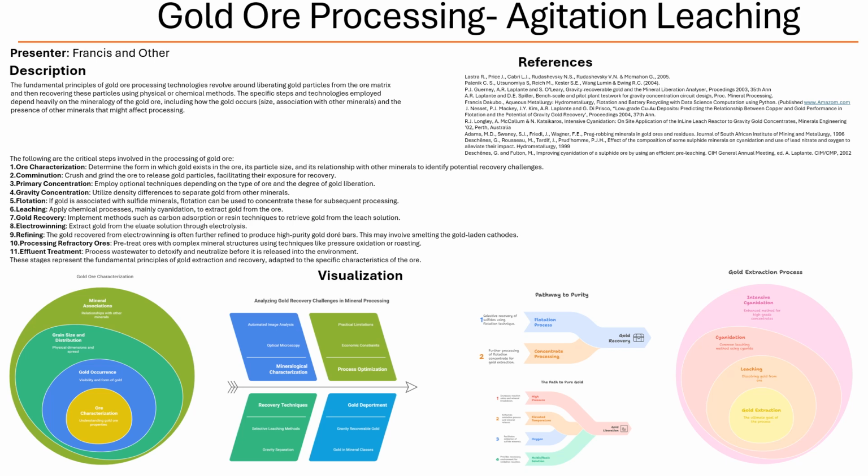That's the leftover material after the initial processing, right? Yeah, basically the waste rock. But even in those tailings, they found a significant amount of invisible gold. Like 27% of the remaining gold was trapped inside pyrite, another 9% was in arsenopyrite, and get this, a whopping 64% was actually invisible gold, but in such tiny inclusions within pyrite that it wasn't recoverable by conventional methods. So even the waste isn't really waste. There's still gold hiding in there. Exactly. It highlights the need for more advanced and targeted extraction techniques.